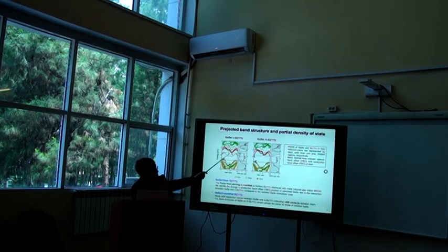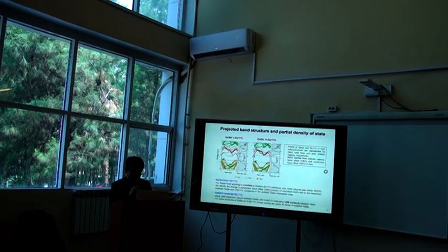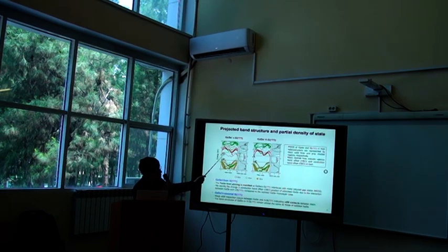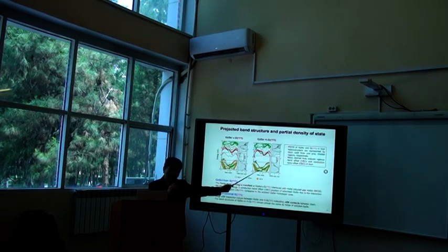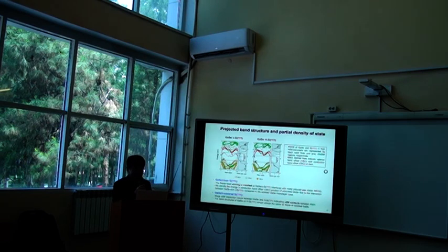And this is the band structures, and this is the projected density of states. Using the clean silicon surface, now you can see Fermi level pinning is clear at the interface because there are some gap states in the band gap region. And in the other case, using the hydrogen-passivated, there are no gap states in the band gap region, which means there is van der Waals contact between the two materials, and the band structure of gallium selenide on the hydrogen-passivated is almost the same as in the two isolated cases.